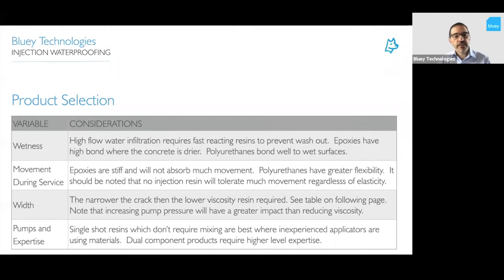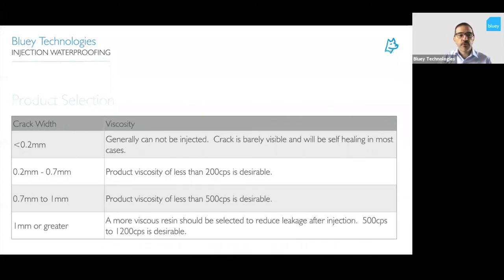When you look at movement during service, epoxies are very stiff. They don't absorb much movement, but polyurethanes will have greater flexibility, particularly the hydrophilic ones, as we spoke about, because they'll actually expand with the crack. The width of the crack becomes important. You usually want a thicker resin in a wider crack, and a very low viscosity resin, very fluid, in a narrow crack. And then the pumps and expertise available to you will also determine what you use. If you don't have the expertise needed for a three-component product, then obviously you're going to be looking at a single-component product. These are all the types of things that you'll be considering during your product selection.